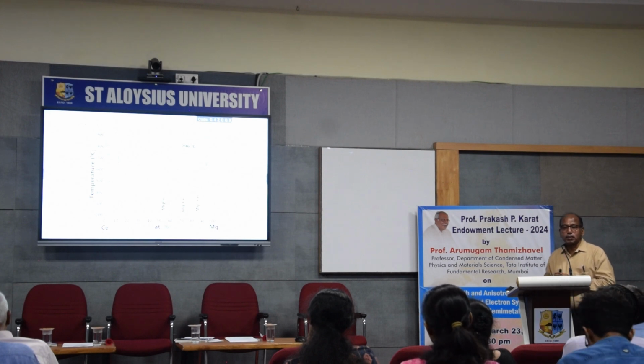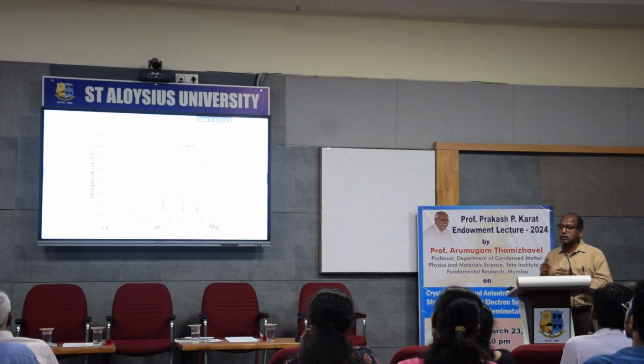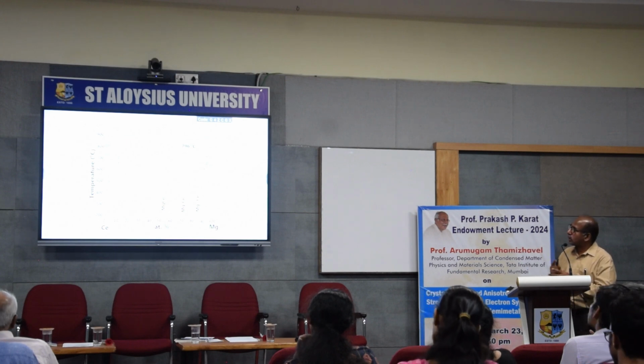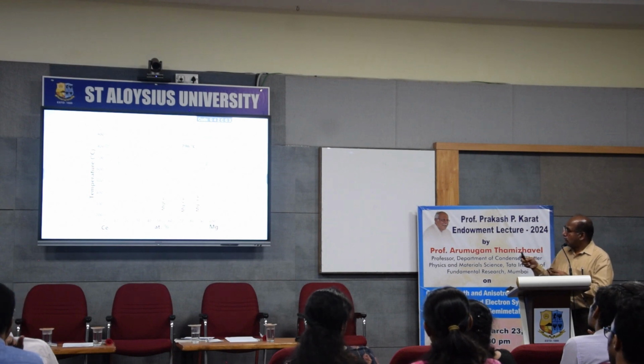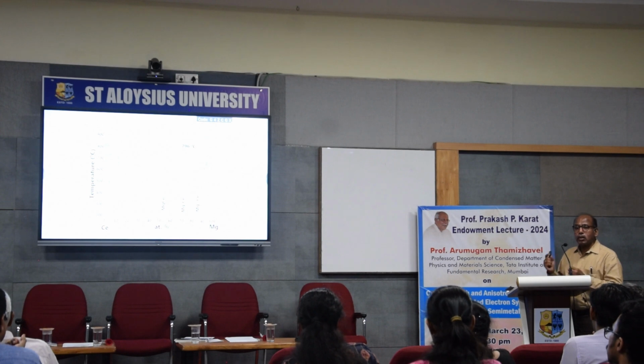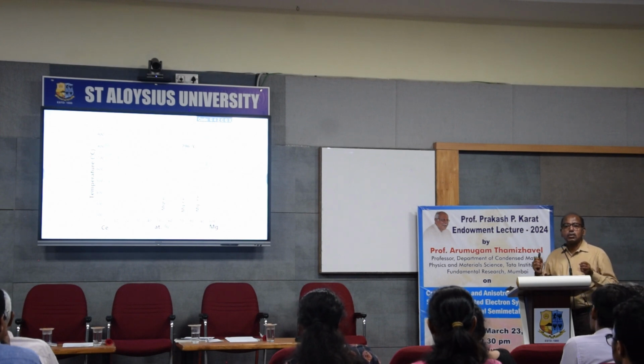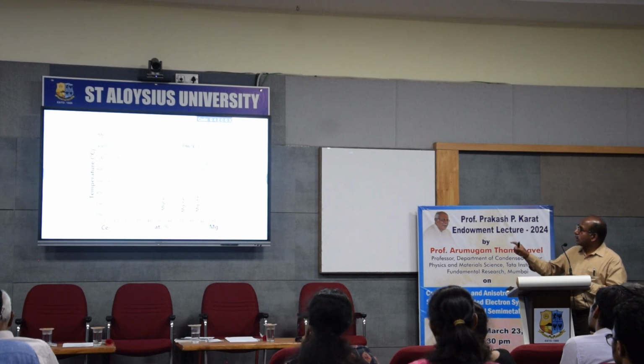And so, as I told you, my interest is in magnetism-related things, and cerium is one of the magnetic compounds, as I just explained to you, because there is one f electron which is unpaired, and it shows magnetism. We wanted to grow the single crystal of cerium magnesium 3. So if I want to grow the cerium magnesium 3, first I look at the binary phase diagram of cerium and magnesium, and I find that it melts at 796 degrees centigrade. That means it melts at 800 degrees centigrade.